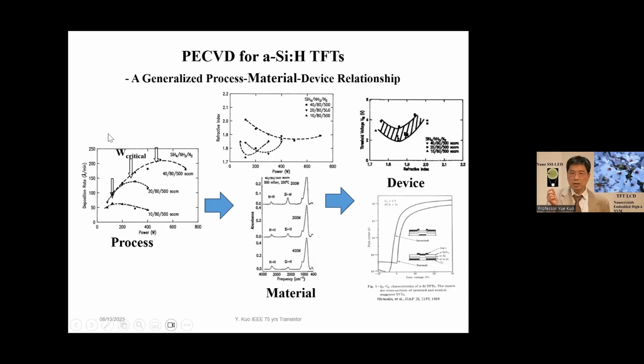In plasma CVD deposition of silicon nitride, there is a critical power. This critical power is the maximum power that can be applied to achieve the highest deposition rate. That critical power affects the refractive index of the gate dielectric, which can be further monitored in the film properties. For the Si-H and N-H bonds, as power increases, Si-H decreases and N-H bonds increase. Further, the stress of the film changes from tensile stress to compressive stress from low power to high power. In other words, the process can be directly related to material properties.